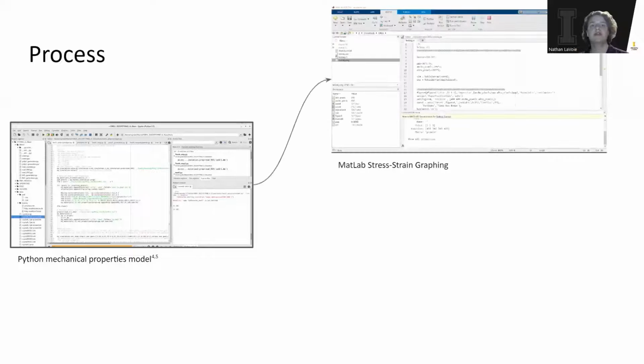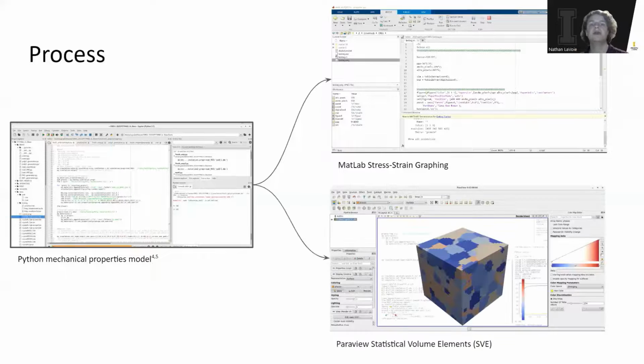The results were then transferred into MATLAB to create stress strain curves and grain size graphs. The data was then compared to experimentally tested Inconel 718 samples with comparable grain sizes. The Python data was also imported into ParaView, where the microstructure data was used to create statistical volume elements, SVEs, to visualize the crystalline grain structure.